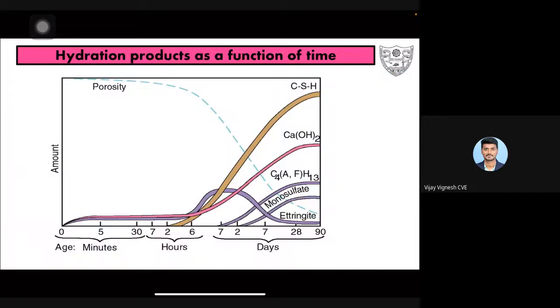Now with respect to the porosity, initially the concrete has 100% porosity, hydrated cement paste or concrete, whatever it may be. Once this reaction starts, this porosity is filled by components such as ettringite, CSH, calcium hydroxide, C4AFH, and so on. Initially the porosity is high, but after 2 days, 3 days, 7 days, 14 days with respect to the cement, the porosity goes down, as the area is filled by solid matter.